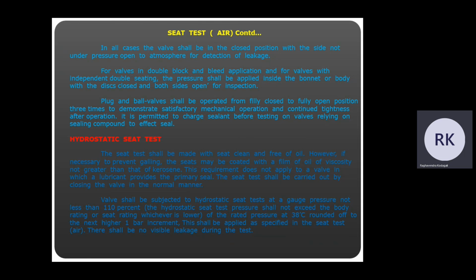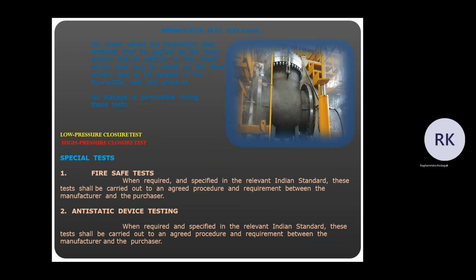The seat test shall be carried out by closing the valve in the normal manner. The valve shall be subjected to hydrotest pressure at gauge pressure not less than 110% at 38 degrees, rounded off to the higher 1 bar increment. This shall be applied as specified in the seat test. There shall be no visible leakage during the test. For check valves, the hydrostatic seat pressure shall be applied on the downstream side. In addition to this, the check valve shall also be tested on the downstream side to 25% of the hydrotest pressure. So also no leakage is allowed.